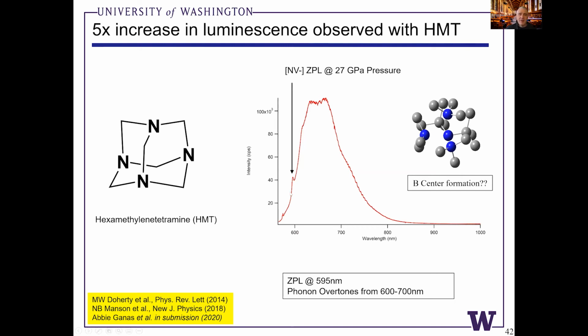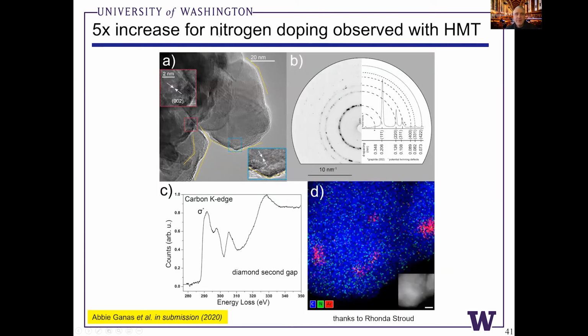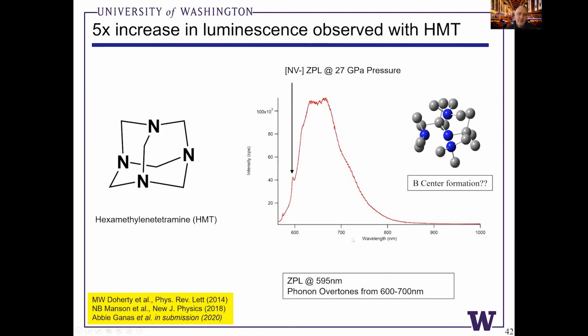The other thing I wanted to share is some recent optical properties of these nitrogen-doped diamonds. This is the hexamethylene tetramine-doped diamond. I forgot to mention, there's a 5-fold increase of nitrogen in the carbon materials we make with HMT as opposed to without. We can see this in terms of X-ray EDAX spectral intensities, and we've also done some elemental analysis to show there's about 5 times as much nitrogen in the molecularly doped samples as compared to the undoped samples.